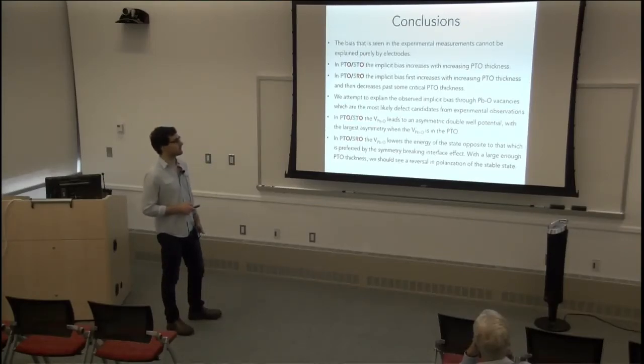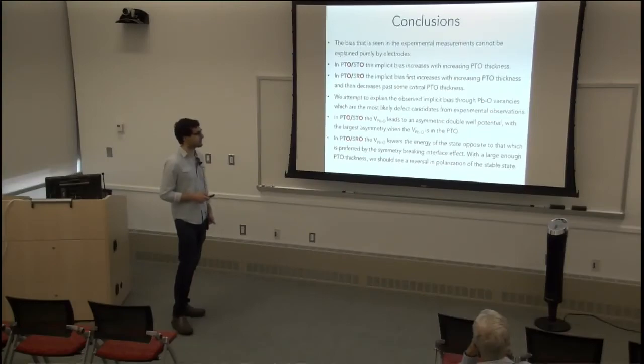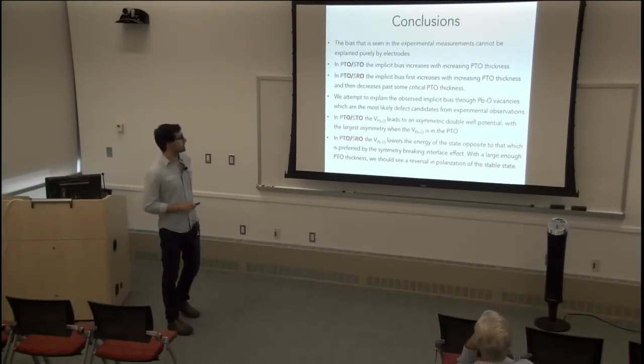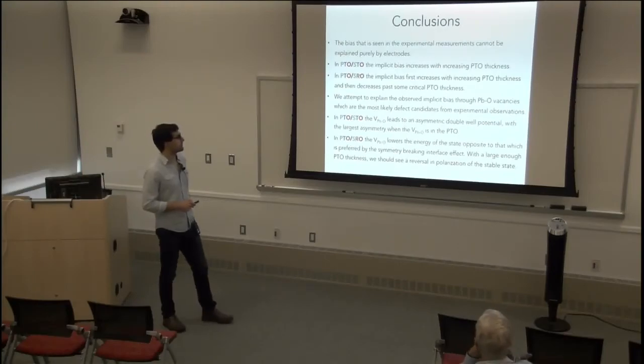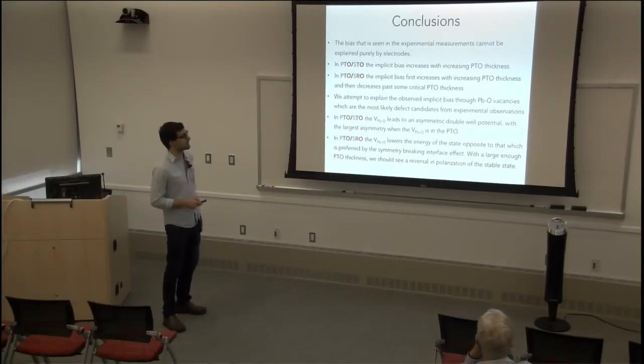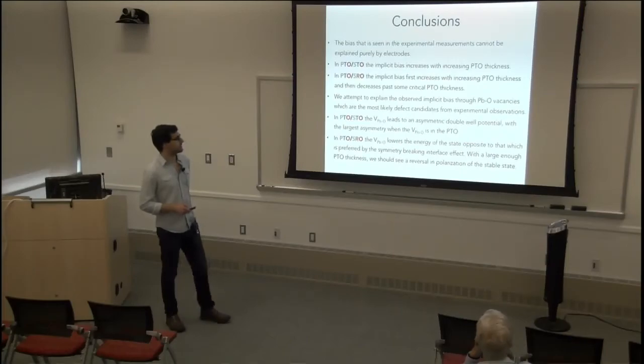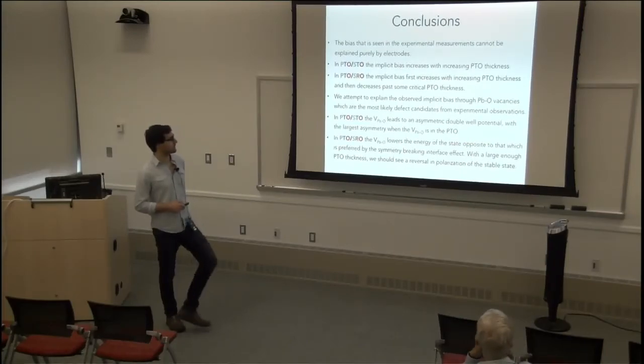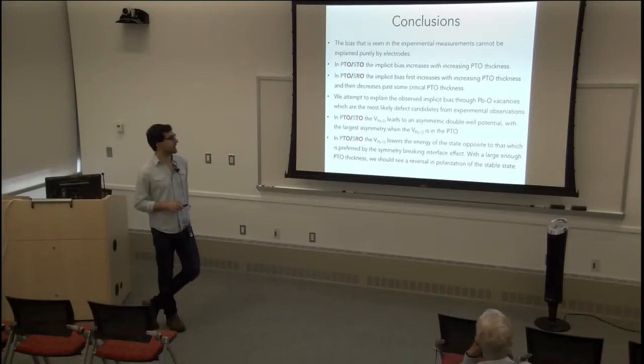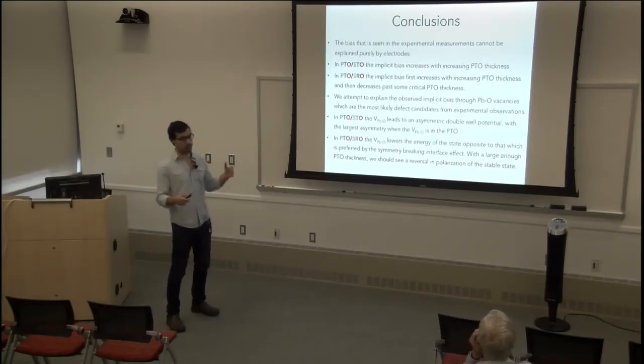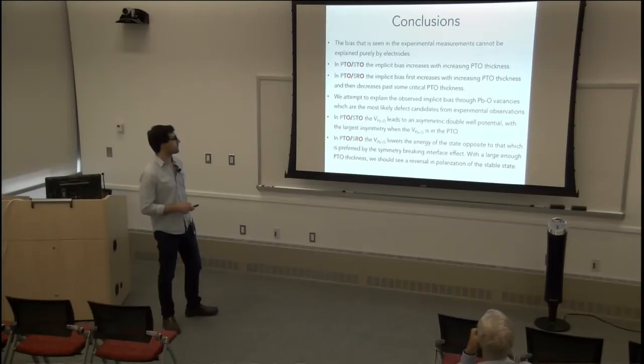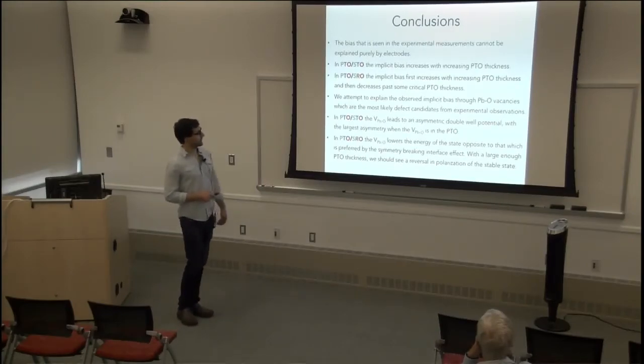based on indirect experimental measurements that we have. And so it turns out that these divacancies do lead to an asymmetric double well potential, which leads to a shift in the hysteresis or capacitance measurement. And in lead titanate, strontium titanate, the largest asymmetry is when you have the divacancy in the lead titanate. And so as we have more and more lead titanate, you have more and more of these large asymmetries coming from the divacancy. And finally, in lead titanate, strontium ruthenate,